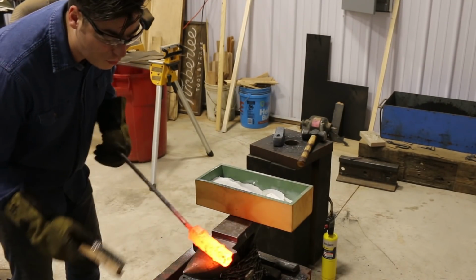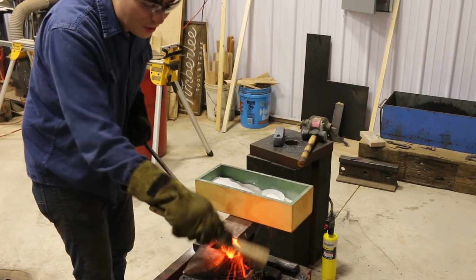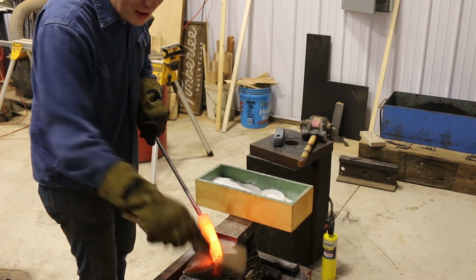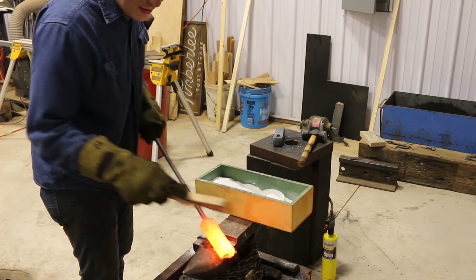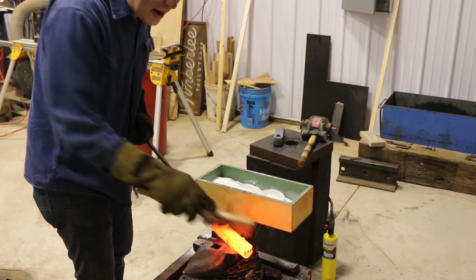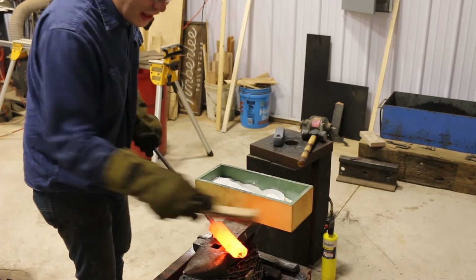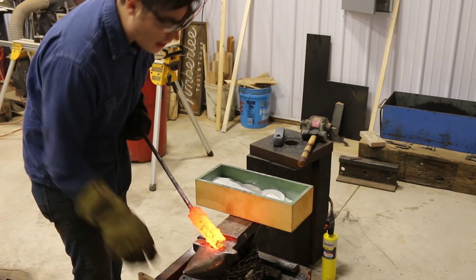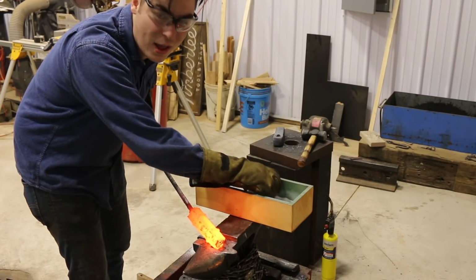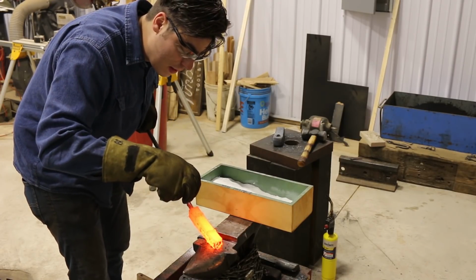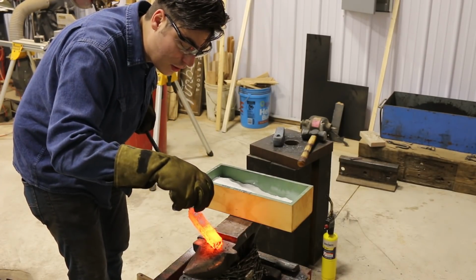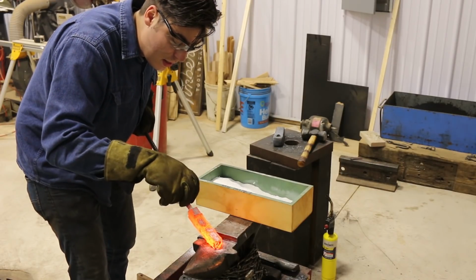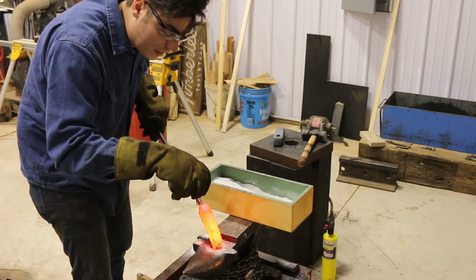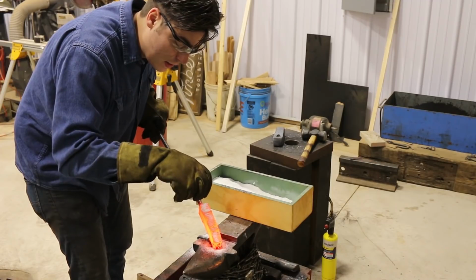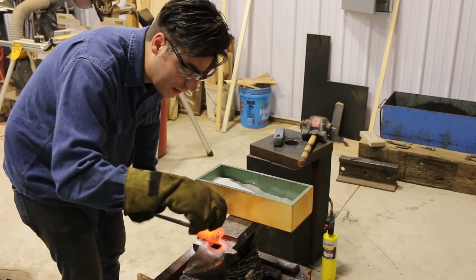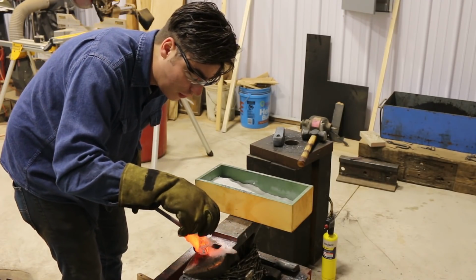So we just compressed this billet. We only really pressed it down about 1/8 of an inch just to make sure that that billet is set. So what I'm doing right now is I'm getting the scale off of here. And now I'm going to go ahead and flux this one more time just to be safe. That way if there's any little areas that didn't compress and may have some scale or oxidation, I can go through this again without having any issues. Right back into the forge.